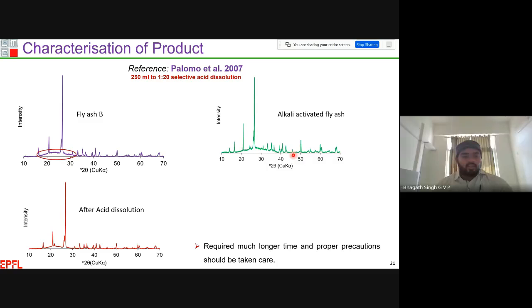And maybe I can show it somewhere here. We can see a clear amorphous portion from 15 to 32, whereas in alkali activated materials we have two different new crystalline phases along with a broad amorphous hump. One moves from lower angle 2 theta, another at higher angle 2 theta.